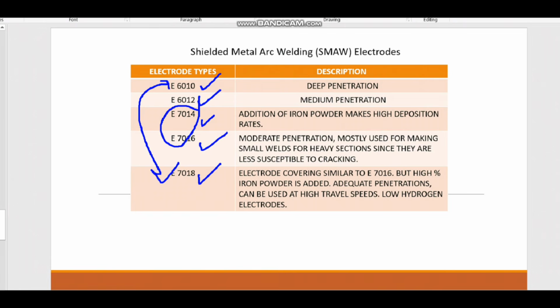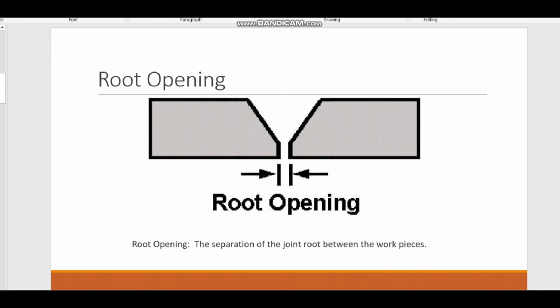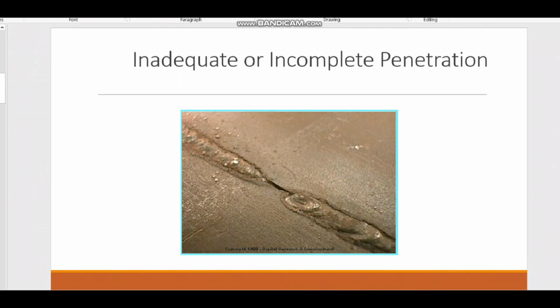So 6010, the highlight of this electrode is that it is used for deep penetration. Deep penetration means, as I told you, we have the root welding. Initially when you weld from the top side, the weld metal, the electrode, has to reach till the bottom and it has to provide proper root filling. So this is very important. That's why it should have proper deep penetration. If deep penetration is not there, what will happen? Incomplete penetration will happen on the next side of the weld. That's why we should have an electrode that has very deep penetration, and that is the only reason we are selecting the E6010 electrode for the root welding.